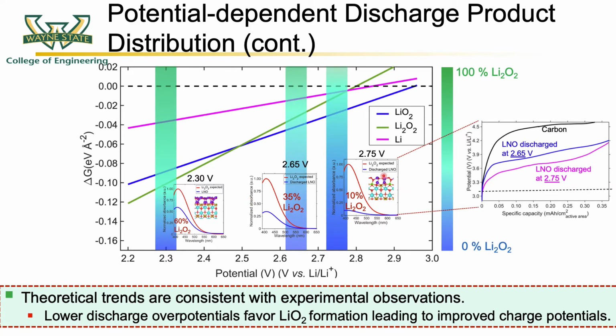To validate the formation of LiO2 and lowering of the charge overpotential losses, we discharge cells at constant potentials of 2.75 and 2.65 volts on the rod-shaped LNO containing electrodes.